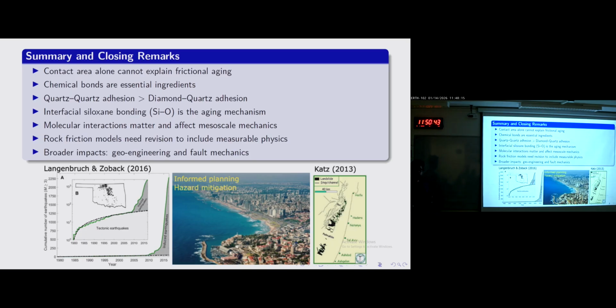I've shown you that contact area alone is not enough to explain frictional aging in rocks, and that chemical bonds are a necessary ingredient in that. You also saw that quartz-quartz adhesion is greater than chemically inert diamond-quartz adhesion, and the reason for that is that interfacial bonding, silicon-oxygen bridges, is the aging mechanism. The problem is that this physics is lacking in almost all friction models today.